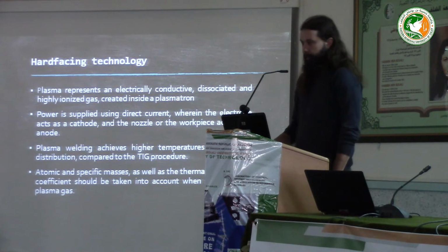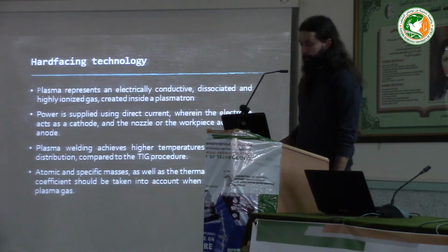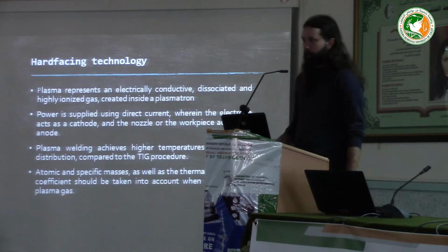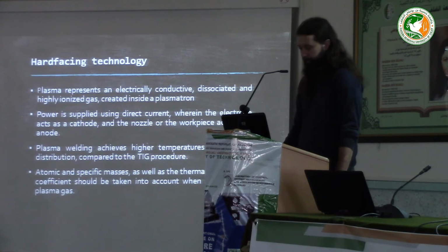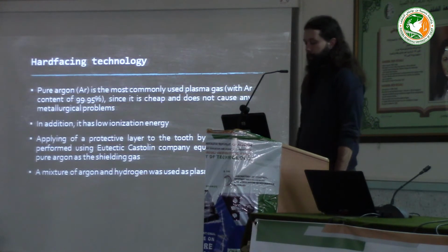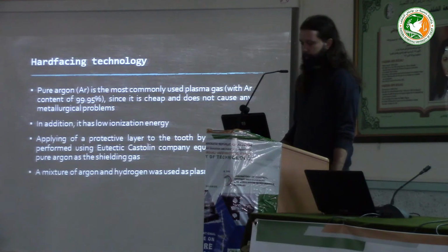And now, well, the important aspect for plasma welding is the gas that is used. When choosing the gas or a mixture of gases, one should have in mind the atomic and specific masses, as well as the thermal conductivity coefficient, which is of great importance when selecting the plasma gas. Also, it is preferred for these gases to have lower values of ionization energy. Normally, pure argon is used for plasma gases or gases with a very high argon content, because it has many advantages. It is inert, so it doesn't react with other materials, it doesn't cause metallurgical problems, it has low ionization energy, and of course it is cheap.